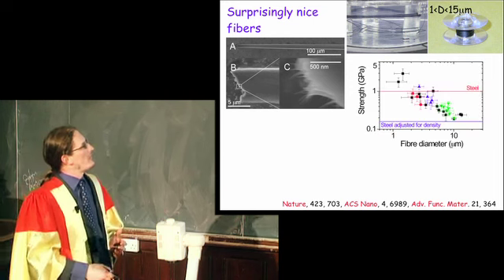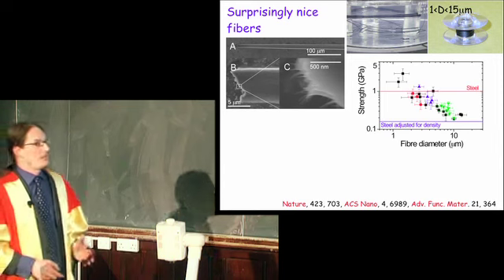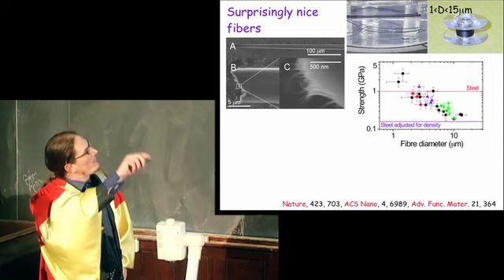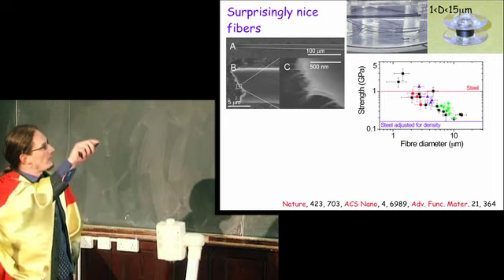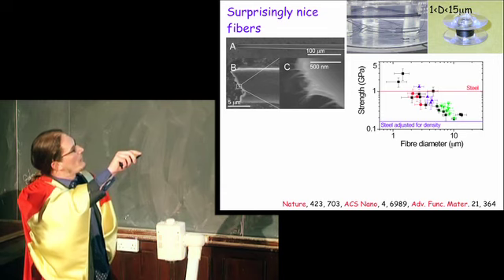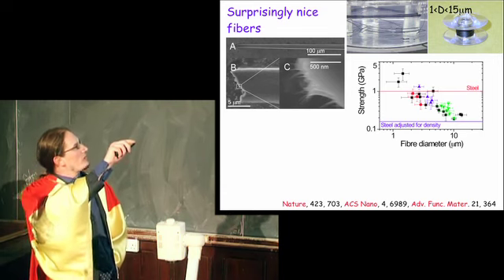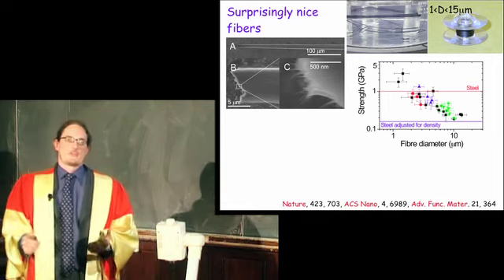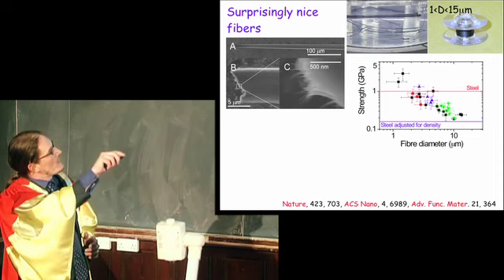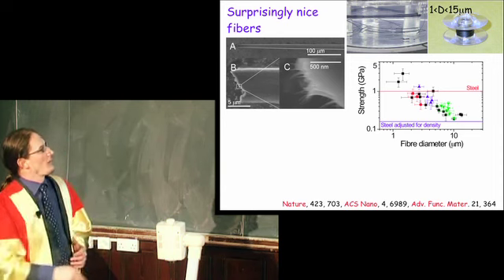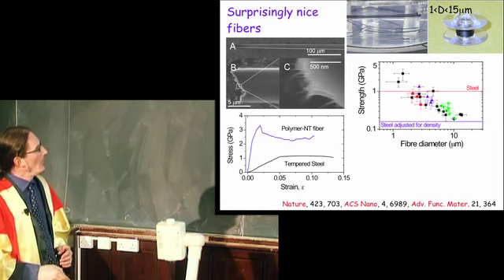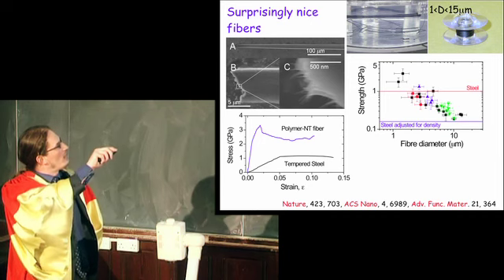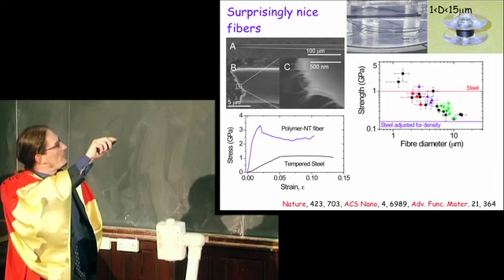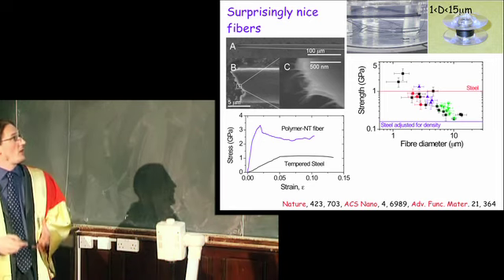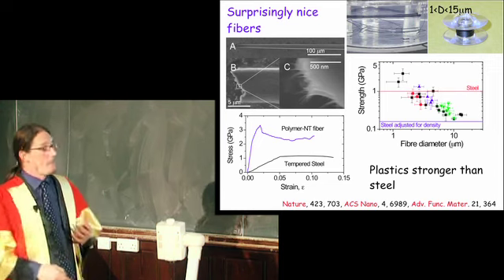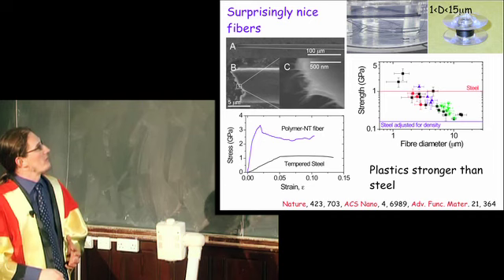Now, let's look at their mechanical properties. One of the things we did is that we measured the strength as a function of the fibre diameter. And what we find is a very, very strong diameter dependence. I won't bore you with the details, but we understand exactly why this occurs. We find that for fibres below a diameter of a few micrometers, they become stronger than steel. Now, it's important to note that steel is much, much denser than any plastic. So when you correct for density, all of these fibres are better than steel on a strength per weight basis. This shows an example of the mechanical properties of one of the better fibres. This is steel, this is one of our fibres, and our fibres are 3 times as strong as steel, many times as stiff, and many times as tough. So these materials really are interesting.